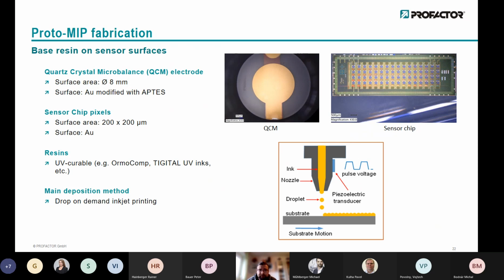We thought of two different sensors here. On the one hand, we have our own QCM setup, so we tested our MIPs on our QCM. Here is an example of our transducer, and on the other hand, the sensor chip by the respective partner in the project, which you see here in a blue colorish scheme, the sensor pixels themselves, so the 64. We managed to coat each pixel individually with inks and get down below 600 nanometer on layer thickness, and also played around with different materials here, to see what suits best.